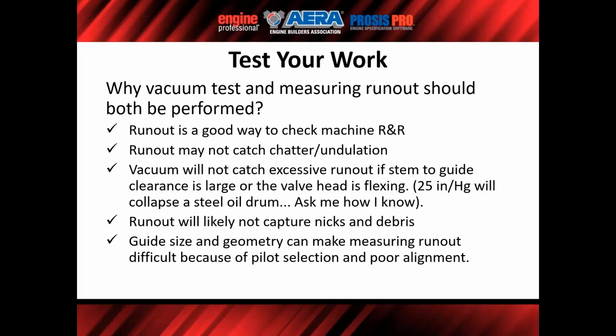And then guide size and geometry can make measuring runout difficult because of pilot selection and poor alignment. So if I measure valve seat runout, turn the pilot 90 degrees, 180 degrees, and I get a completely different result, then you start looking at your tooling and your setup. If you don't change it, you just pull it out, you put it right back in, and you got a different result, again, you're chasing your tail. So test your work.